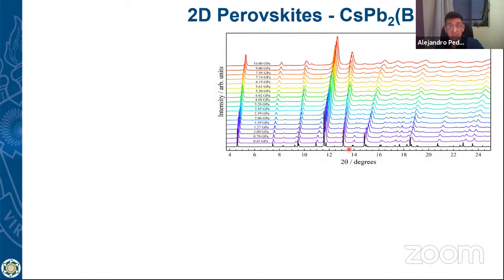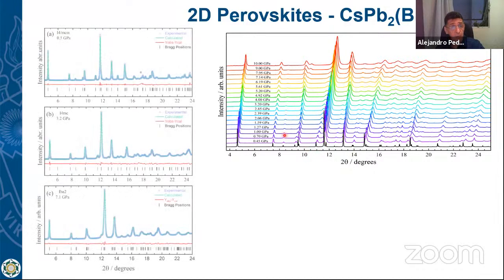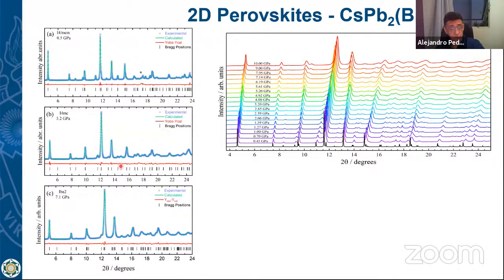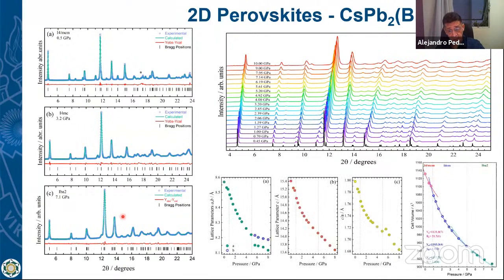We studied this in the synchrotron when we measured X-ray diffraction as a function of pressure, and we were able to determine the crystalline structure using Rietveld. And we have confirmed with X-ray diffraction the structural phase transition, but we are interested in trying to understand how the structure is related to the luminescence.